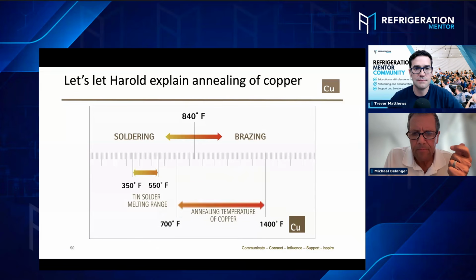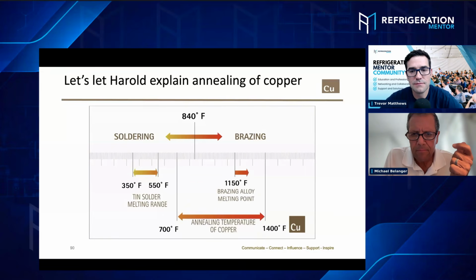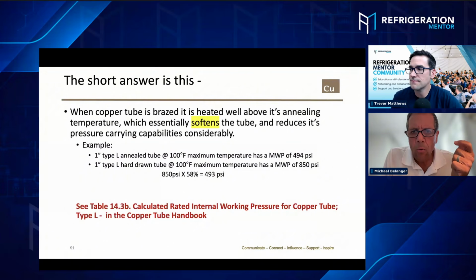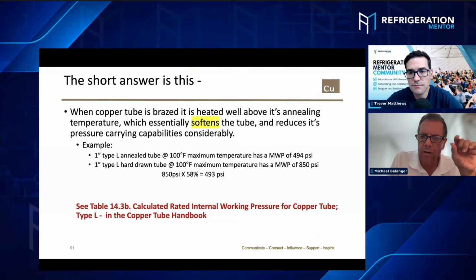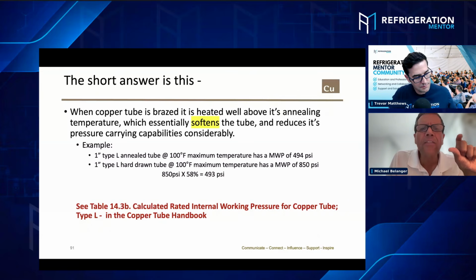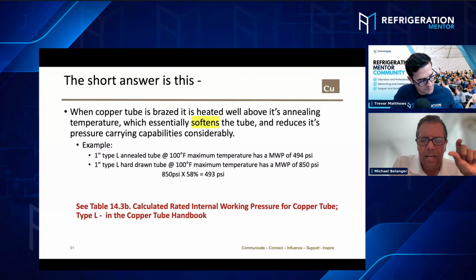And most brazing alloys have a melting temperature above 1150 degrees Fahrenheit, well above the annealing temperature of copper. Why that's important: where I've highlighted, it softens the tube. The joint is still powerfully strong, but the maximum working pressure of the joint, because the tube has been softened, has been lessened almost in half in the case of 1-inch type L. Okay, all this information, folks, it's all in that free documentation that we give you in the Copper Tube Handbook.